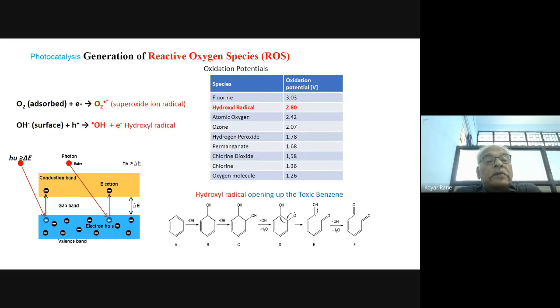In photocatalysis, there is mainly a generation of reactive oxygen species by irradiating semiconducting metal oxides. You can see that when the electromagnetic wave is impinged on the semiconductor, electrons are excited to the conduction band and holes are formed at the valence band. There is adsorbed oxygen present on the semiconductor, which will react with the electron thus released, forming superoxide radical. As well, the surface hydroxide or surface moisture present on the semiconductor reacts with the holes formed and reactive hydroxyl radical is formed.